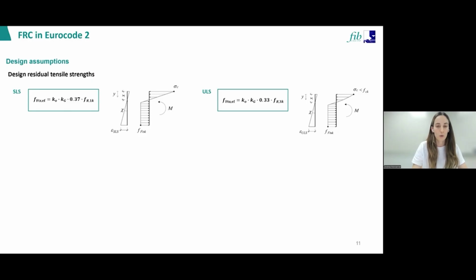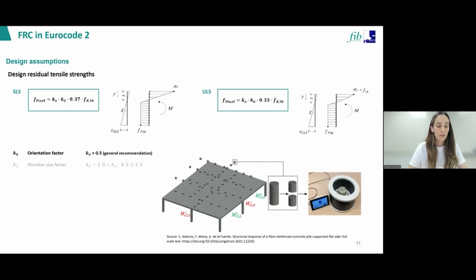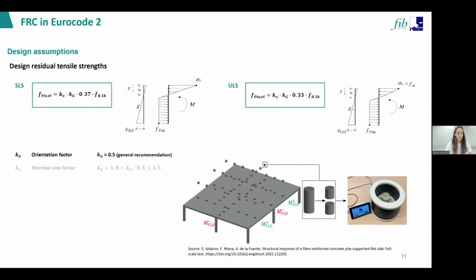size factor. The fiber orientation factor accounts for the fact that the fiber distribution and orientation in the actual structure may significantly differ from those obtained in the standard laboratory beam test. In practice, fiber orientation is strongly influenced by casting procedures, concrete flow, member geometry, or the placing conditions. For this reason, Annex L allows, for example, the orientation factor to be experimentally assessed through representative tests performed